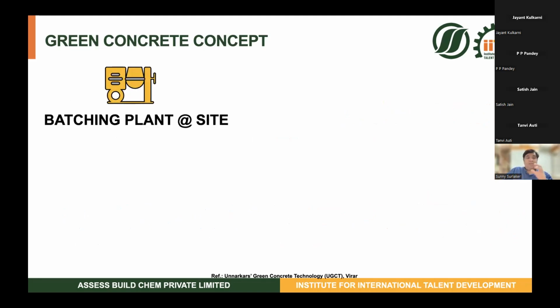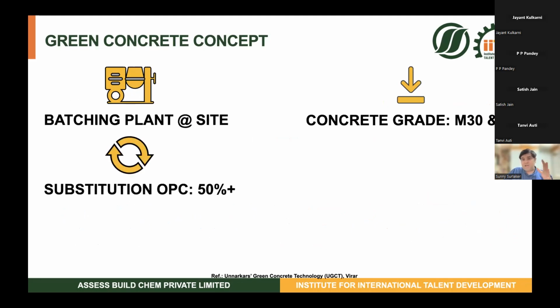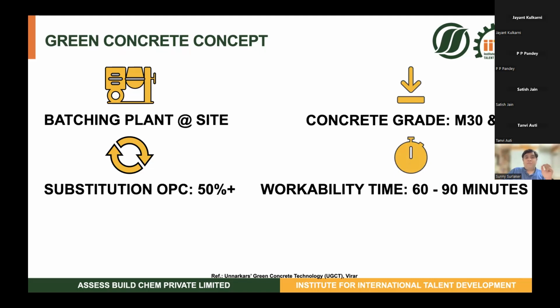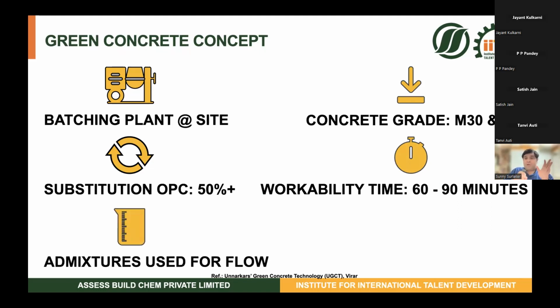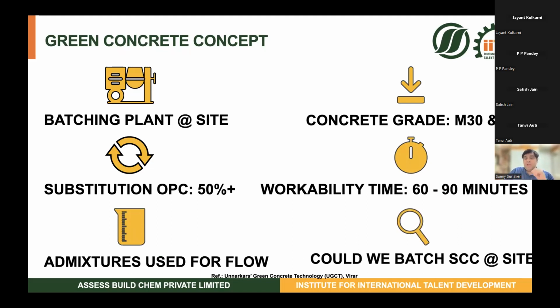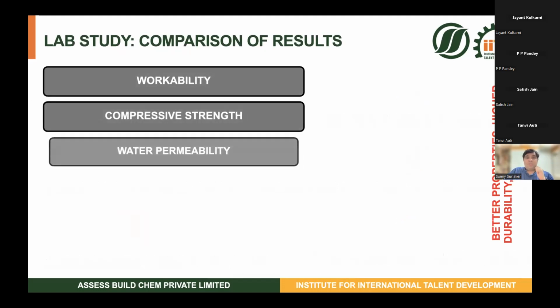As a concept, we started by trying to batch this kind of material at site. We had a nice pan mixer at site. The initial types that we did all had a low concrete grade, only about 35 MPa. We substituted more than 50%, close to 50 to 55% of the OPC with slag. We had a good workability time, so the admixtures were designed especially to give a particular kind of performance. And this then led to the next project where we thought, could we do SCC at site? The answer to all of that was yes.